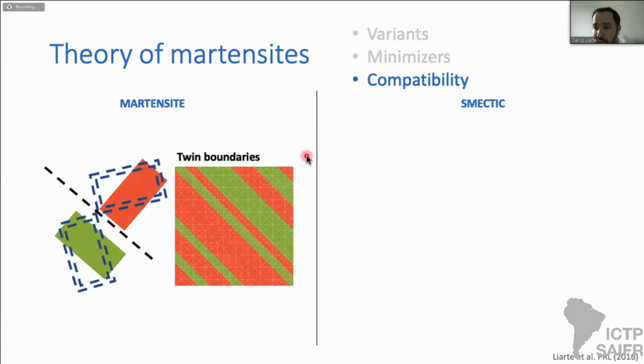So now comes the last part of the theory of Martensites that I wanted to discuss, which is the compatibility conditions. So these crystal Martensite variants rotate and form twin boundaries in the form of planes, or lines for the two-dimensional case. Now, this compatibility makes it possible for the crystal to accommodate this deformation of the unit cell when the boundaries of the sample are constrained.